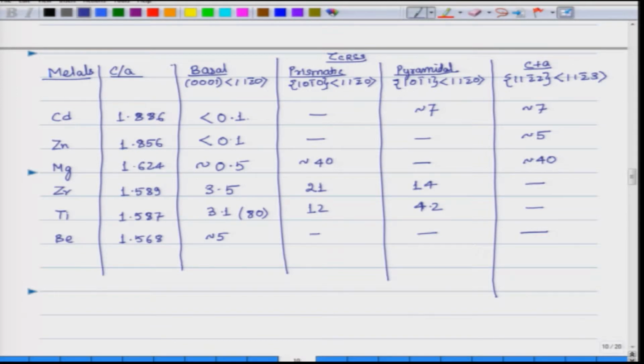Okay, so that is the slip system preference based on the tau Pn values. Now, let us look at what are the possible Burgers vectors. So, we have seen C and A, but those are only when we have the full dislocation. There is also a possibility of partial dislocations, which is similar to what you see in an FCC system. And not only that, the similarity to FCC does not end there. In FCC, if you remember, we talked about Thomson's tetrahedron, which gives you all the possible slip planes, partial dislocations, Burgers vectors and so on.